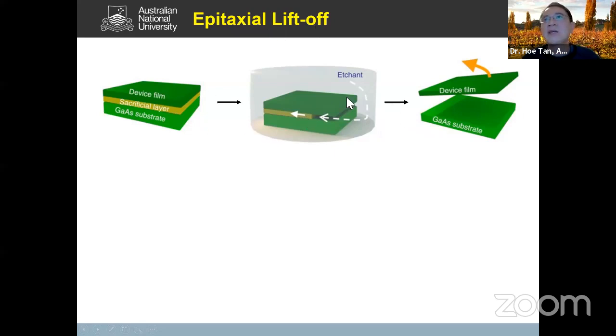Okay, shown here is the schematic of how this works. So you start off with your substrate, and then during layer growth, we grow a sacrificial layer, and then grow your device layer on top of this sacrificial layer. Okay. So the important part of this sacrificial layer is it must be selectively etched in some particular etchant, and the device layer is not etched by the etchant. Okay, so there must be selectivity between the sacrificial layer and the device layer. And you put the whole thing in some etchant, usually some kind of acidic solution, and then it'll gradually etch this sacrificial layer, and then the whole device layer is peeled off.